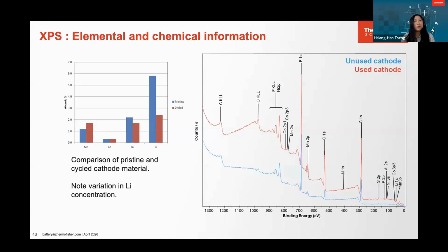Okay, so we can immediately see the difference between the two conditions, and this may be important for the first use of the cathode. So for example, the binder may become mobile in the electrolyte, or it can react and form a surface layer that impedes ion transport later on. In comparison, the used cathode sample comes from a cell that had been through several charge and discharge cycles and was in a charged state when the cell was disassembled.